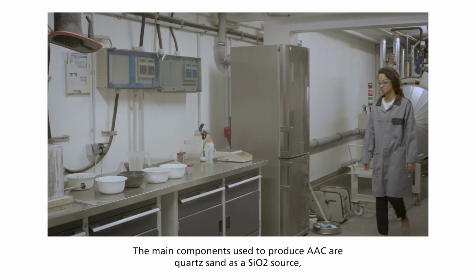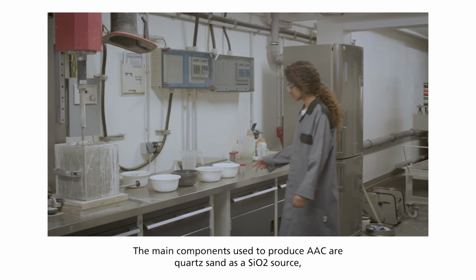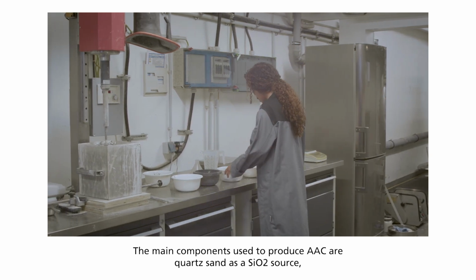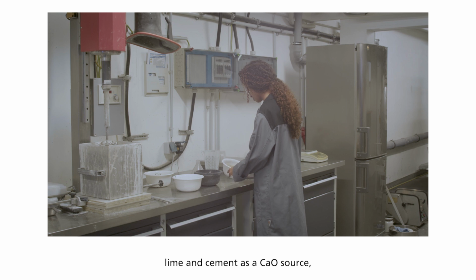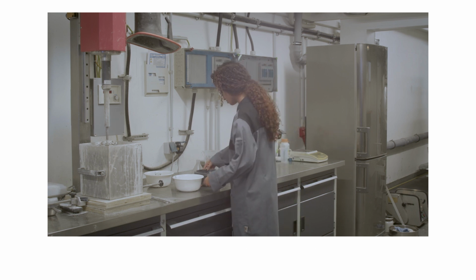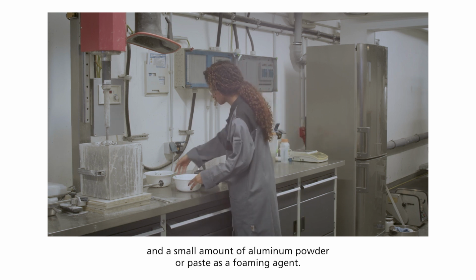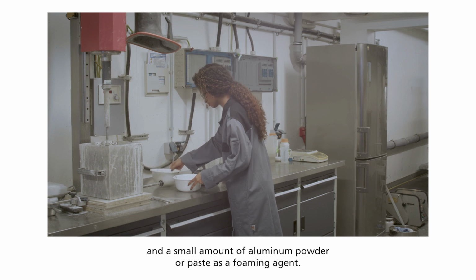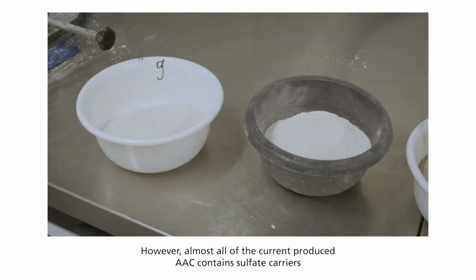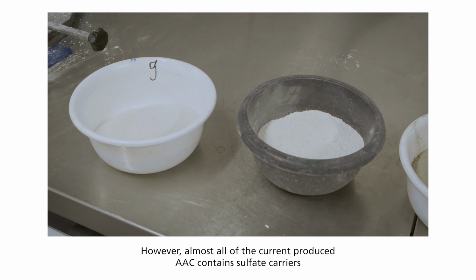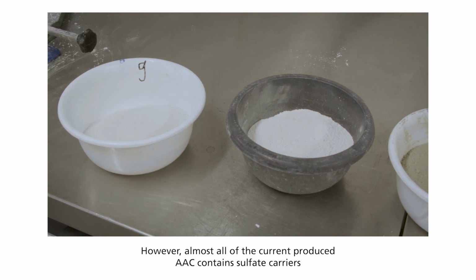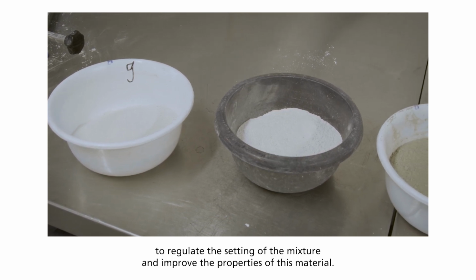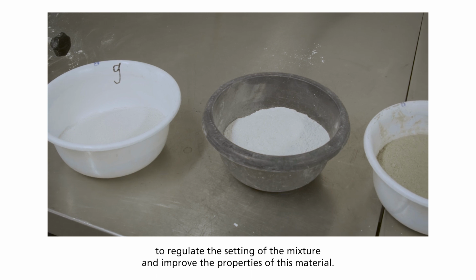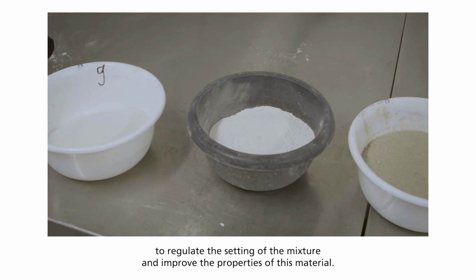The main components used to produce AAC are quartz sand as a silica source, lime and cement as a calcium source, and a small amount of aluminum powder or paste as a foaming agent. However, almost all of the currently produced AAC contains sulfate carriers, to regulate the setting of the mixture and improve the properties of this material.